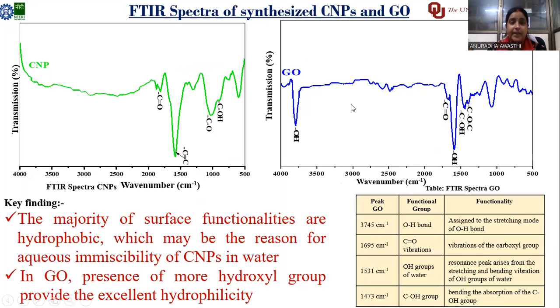As I have said, I have chosen the photothermal materials. For the photothermal material, I have chosen carbon family members. One is CNP, carbon nanoparticles, and another one is graphene oxide. As you can see, there is a spectra of carbon nanoparticle and graphene oxide to measure surface functionality. CNPs are hydrophobic, which may be the reason for the aqueous immiscibility of CNP in water, while GO shows the presence of more hydroxyl groups. Here you can see the peaks designated: hydroxyl groups are present, carbon and hydrogen groups are present.